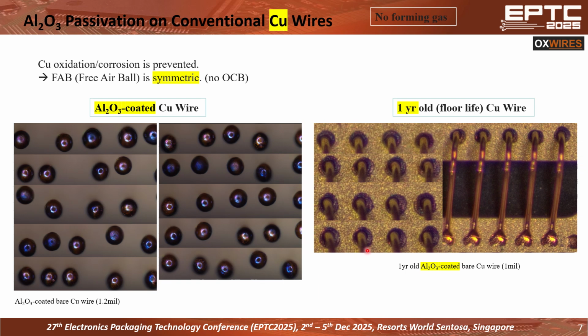And we left the Al2O3 passivated copper wire on the floor for 1 year. But when we did wire bonding operation, we can get a nice wire bonding as well, even after 1 year. I have to emphasize, no forming gas was used.